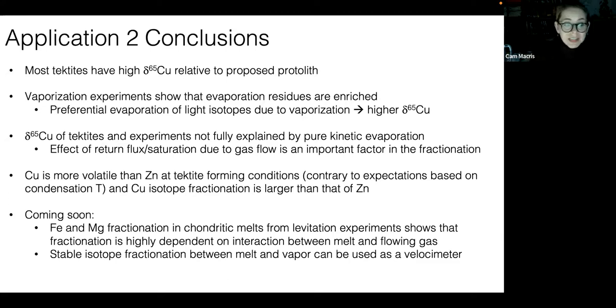And lastly, I would like to just plug a study that we hopefully will have coming out soon. It is in second stages of review, where we look at iron and magnesium fractionation in chondritic melts, also in levitation experiments. And what we see is that the fractionation, again, is highly dependent on the interaction between the melt and the flowing gas. And in fact, in this paper, we say that stable isotope fractionation between melt and vapor can be used as a velocimeter.